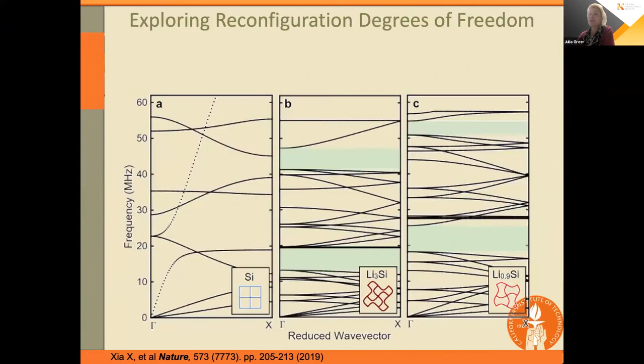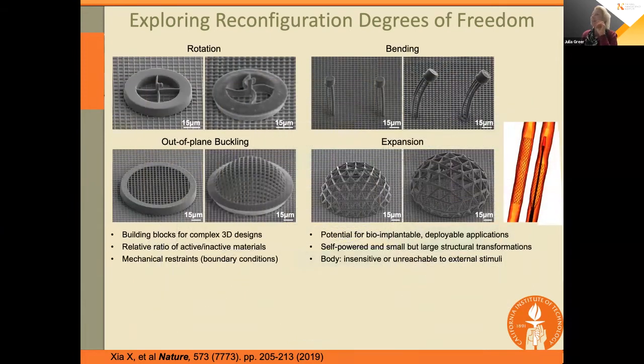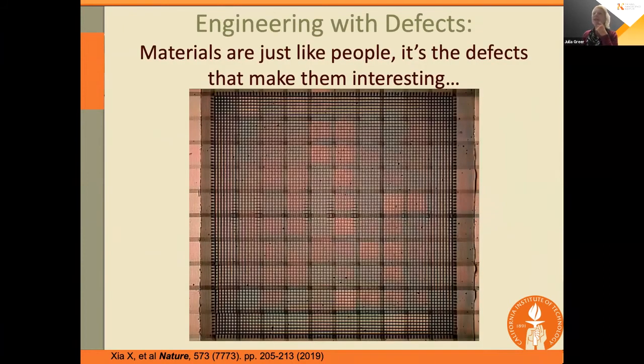Now, what my former student who worked on this project, Xiaoxing Xia, discovered is that depending on the degree of lithiation, you can actually measure the different band gaps that emerge throughout the structure. And so the amount of lithiation, first of all, is irreversible in that as soon as you remove the stimulus, it doesn't go away. And so it locks in that architecture. And that allows us to induce different degrees of freedom, for example, out of plane buckling, as well as expansion and bending. And so what we learned is that you can actually pre-build a particular pattern as long as you understand the defect behavior and how coordinated that buckling is.